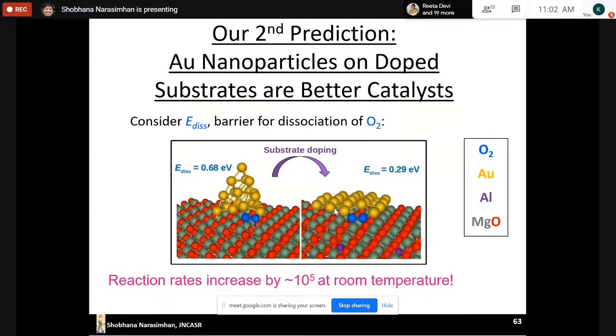And we do indeed find that the energy barrier that has to be climbed when you have the undoped surface and this three-dimensional particle is 0.68 eV. But when you have the doped surface and this flat particle, the barrier is reduced by more than half. So this is indeed a better catalyst, and you have found a way of making a better catalyst.